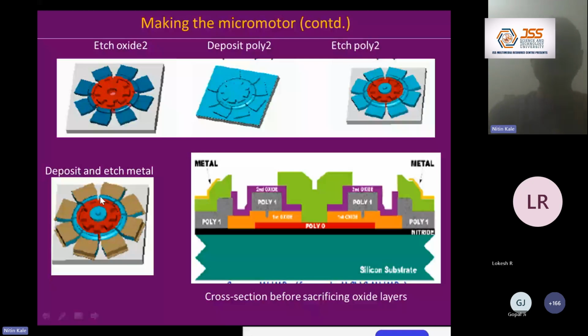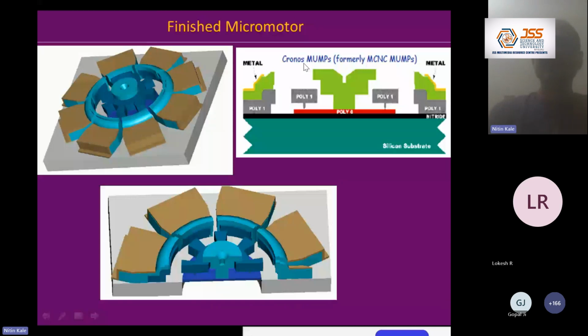Okay, after you etch oxide 2, you deposit poly 2, you etch poly 2, and finally you deposit and etch the metals. Now again, remember, this is the first slide that I showed you. It's something like this, and you need to now remove all the sacrificial oxide. So you see it in cross section, and once you remove the sacrificial oxides, you have all your electrodes, you have a rotor, and you have a stator, and your micromotor is ready. So this was a very popular project in the early 90s, making micromotors. Imagine tomorrow if all the motors or the moving parts inside your wristwatch are changed. You can imagine what's the market size.